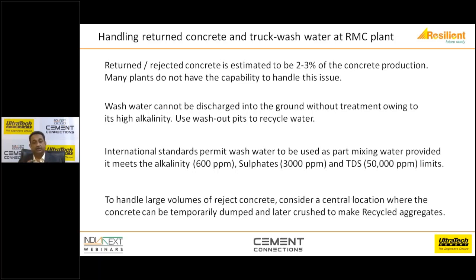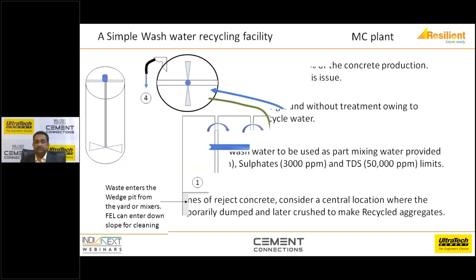Then what happens to the concrete we mentioned, which is coming out in large chunks and is dumped somewhere? In most places you find that rivers, riverbeds, or lakes are full of concrete. You need to collectively find a common place where you can dump the concrete. After the concrete is set, you can crush it and use it as recycled aggregates. You can even use chemicals which will stabilize the concrete overnight, with an activator, and you can use the concrete again. Or you can use some admixtures which can segregate the slurry and the aggregates. So we need to work out how we are going to deal with the situation rather than close our eyes.